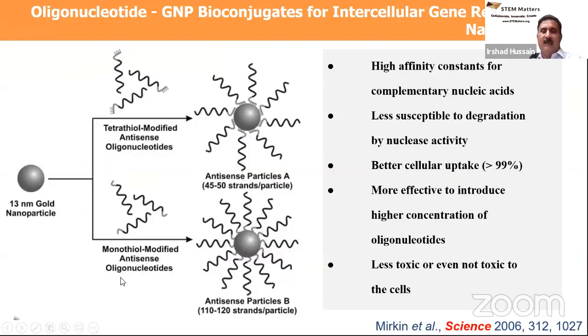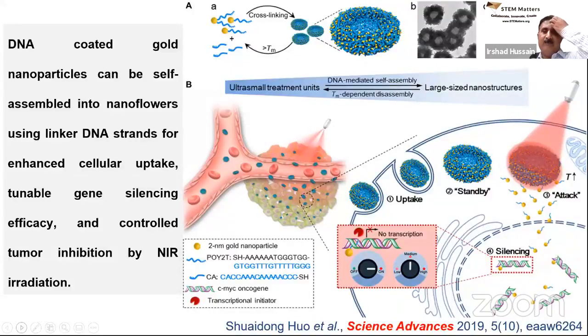And for this purpose, gold nanoparticles have really been found to be useful. In this case, these oligonucleotides, which were initially functionalized with a thiol group, were coated on gold nanoparticles, and due to the complementarity effect of these oligonucleotides, when they are closer to each other, they become much more stable compared to when they were independent. So in this way, they were able to deliver siRNA to the cell without degradation and do the useful job there.